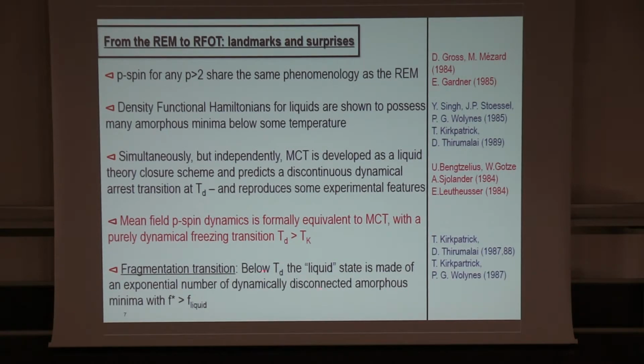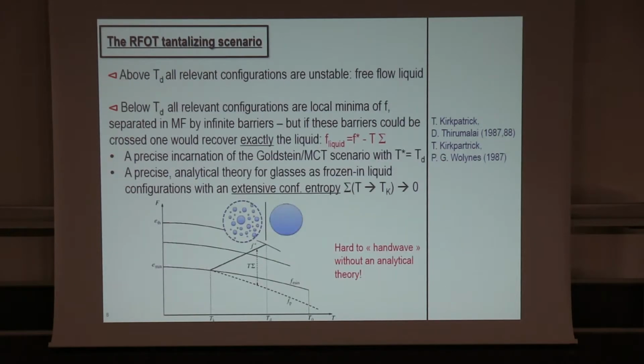And then I think the breakthrough came that these mean field p-spin models have a dynamics that is formally equivalent to MCT with a purely dynamical freezing transition at a temperature Td greater than Tk, the thermodynamic transition of Derrida, if you want, or of Kauzmann. And furthermore, that from a thermodynamical point of view, nothing happens at Td. It's a strange transition, a kind of fragmentation transition in phase space that I'll illustrate in a second, where the liquid state, which is kind of one and unique at high temperature, becomes the superposition of an exponential number of dynamically disconnected pieces. And all these pieces are actually amorphous minima, all of them having a free energy that's larger than that of the liquid. So this is all in these papers. Yes, I've used this kind of side note way to give references, and of course there's a lot missing, but I've selected a few that I find relevant.